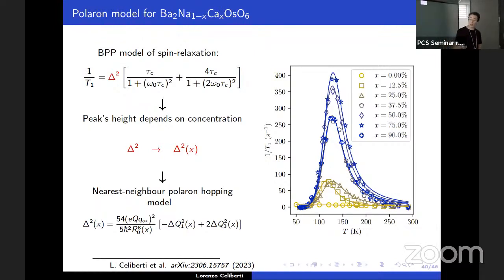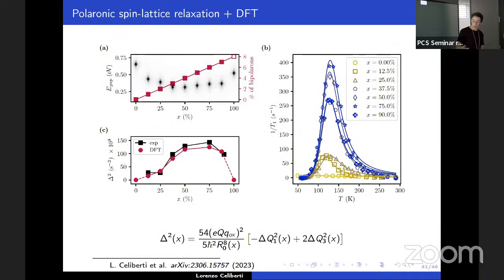And when we look at the comparison between this formula, which is the red one, and the value obtained from the fit, we observe a very nice qualitative agreement between the data. And you see from the DFT calculation, you always obtain an insulating solution. You have a gap which is decreasing a little bit in the middle, but it's always open.